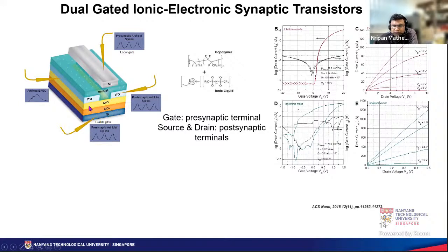So what we did was take this conventional transistor, and we actually built one more gate on top of it. What we put in was a solid state ion gel, which itself is a mixture of this particular fluorinated polymer and this ionic liquid, and then silver as a top electrode on top of it. So we have essentially two gates which could act as presynaptic terminals, and the source and drain electrodes could act as postsynaptic terminals.